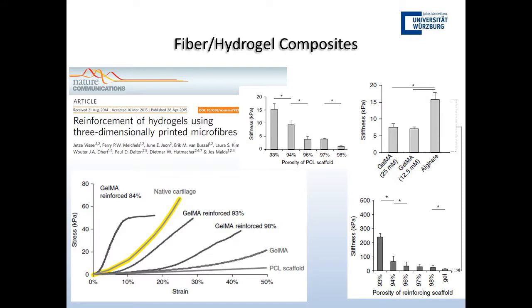So here is this stress strain curve for GelMA. For PCL, it's actually compressive measurements. You could see now we're getting close to cartilage, which was really crazy, because these fibers were both soft and flexible. They had a lot of porosity, and so we could now put cells under quite high mechanical loads without completely destroying the scaffolds. At the same time, FDM scaffolds, and I think here this is an FDM scaffold, this occupies a lot of space. So the porosity of the micro extruded or FDM scaffolds is a lot lower.